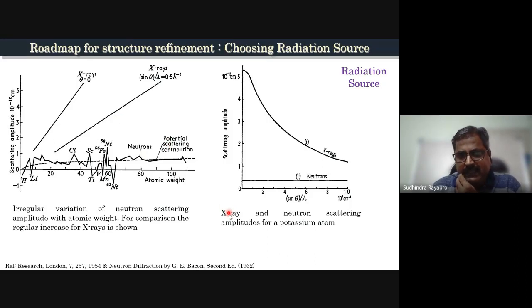Another point is that the form factor, or the scattering amplitude, of X-rays falls off as a function of the angle. What it means is that as you go higher in 2 theta, the intensity of the Bragg peaks comes down. So I think you would have observed this in your XRD patterns. The reason is that the scattering amplitude for X-rays falls off as a function of 2 theta, which is not true in the case of neutrons. Neutrons have an almost constant scattering factor all through the angular region.